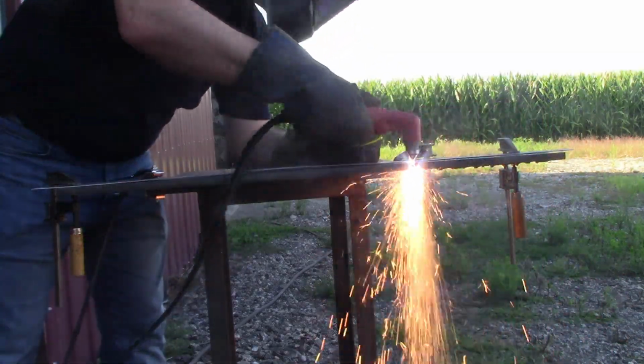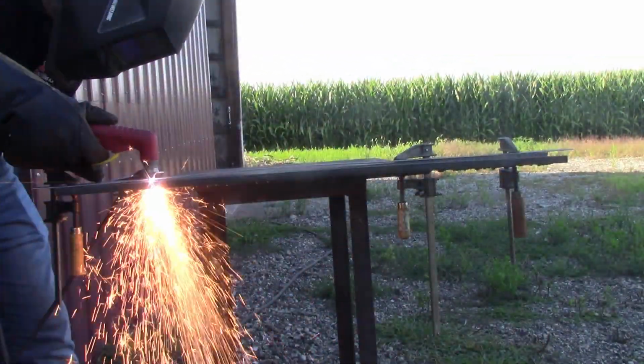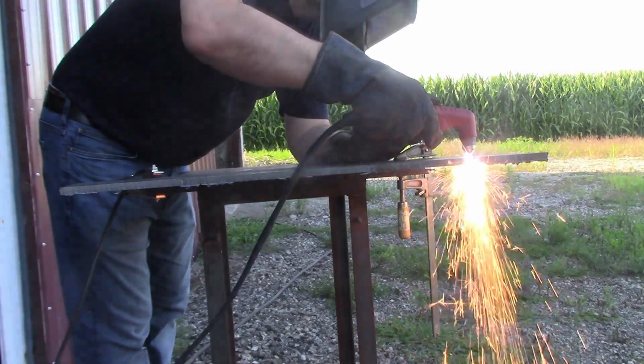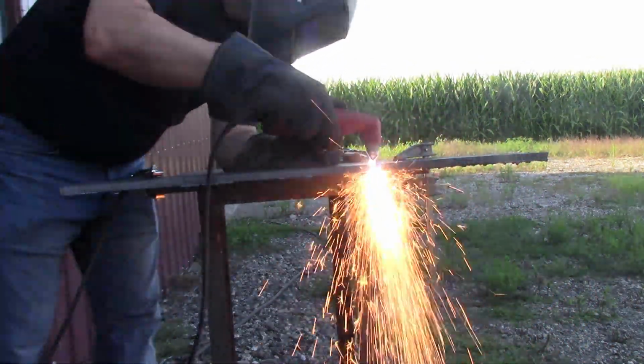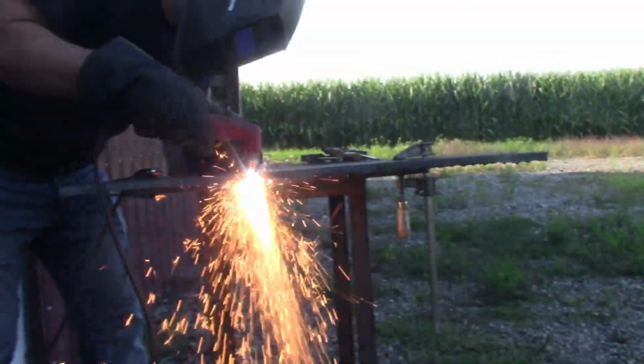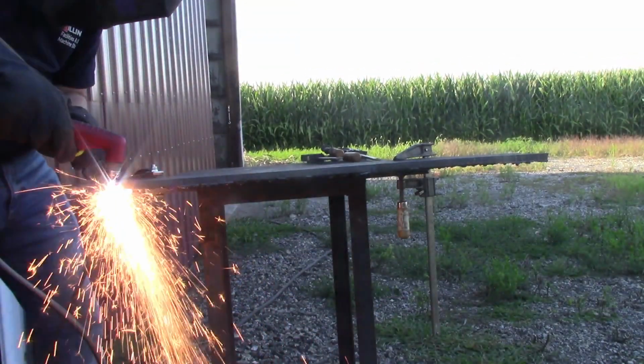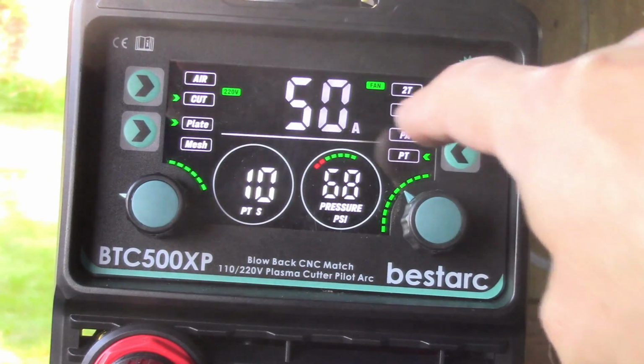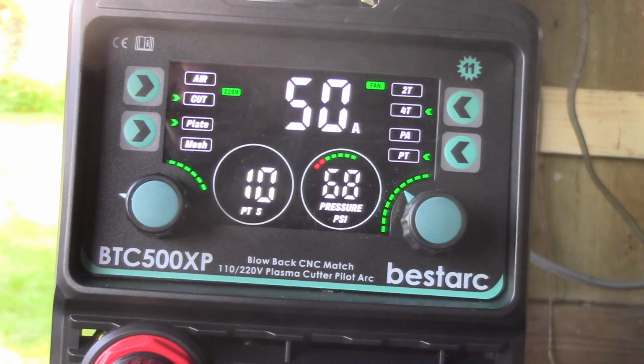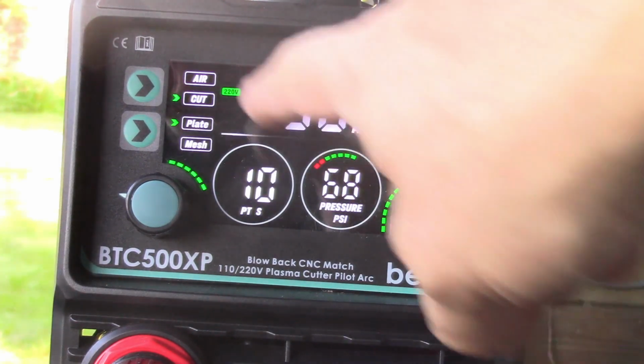Looking back at the footage, it was running for 4.5 minutes on the first cut and then another 4 minutes on the second, with less than a minute between them to reset. That's definitely outperforming the stated duty cycle. The overcurrent error cleared itself after about 3 minutes, at which point the amperage setting returned on the display and air started flowing through the torch just like when it's purging.